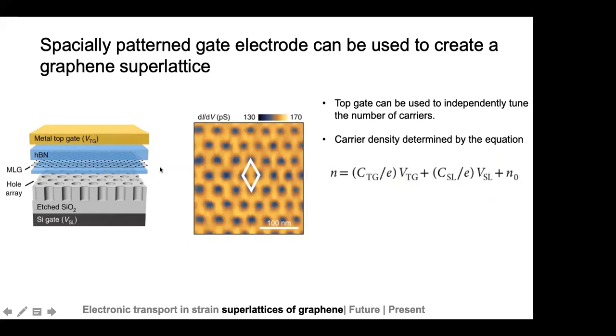HBN is an insulator, and that is why it is very good for encapsulating graphene if we want really clean resistance results, because otherwise the charge carriers impurities from the substrate, the silicon dioxide silicon system, might interfere with the transport characteristics. So they had that encapsulated graphene system placed on top of this patterned silicon dioxide silicon chip, and on the silicon dioxide chip they had a triangular lattice which was created, and they used this silicon gate as